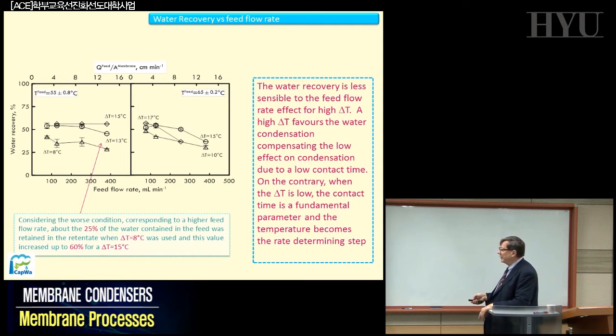You can see here that in the worst condition, that means higher feed flow rate, about 25% of the water contained in the feed is retained, which is more than the expectation. The people sponsoring this project were happy if you just realized 20%, because 20% gives the possibility to become independent. And with a delta T of basically 8 degrees centigrade, which is relatively not too high, you can recover 25%. If you want to recover 60%, much more than necessary, you have to realize a delta T of 15 degrees centigrade, which is the real cost of the process.